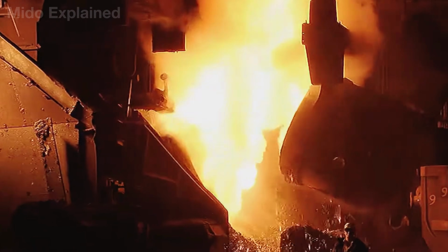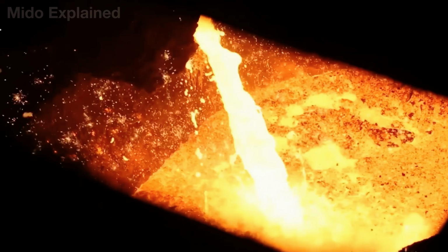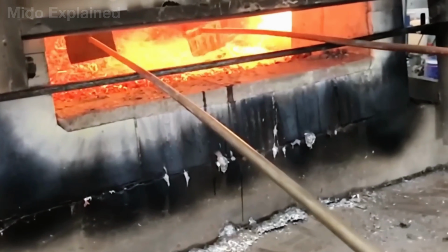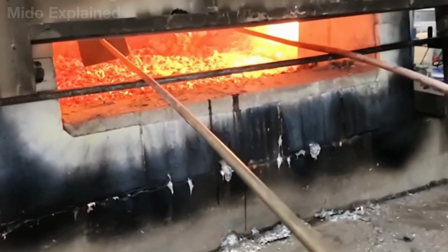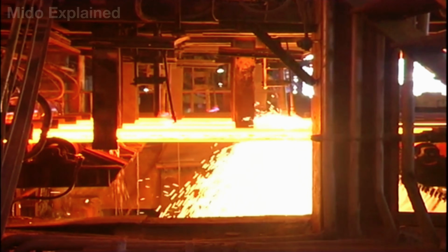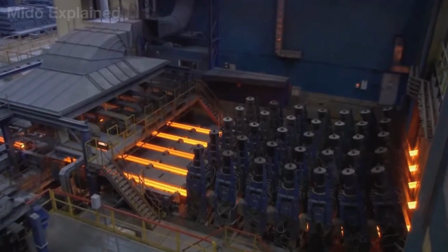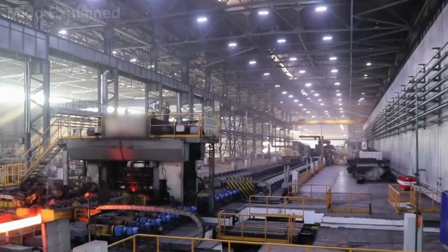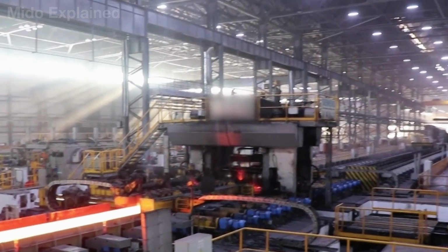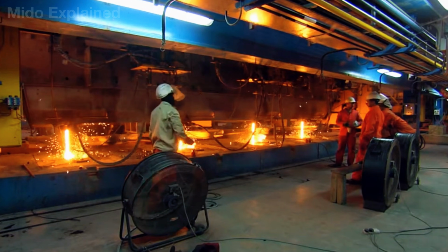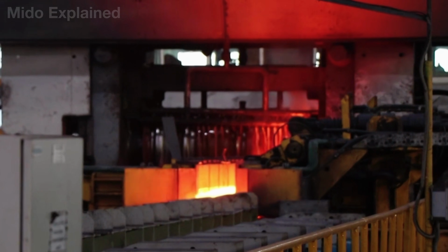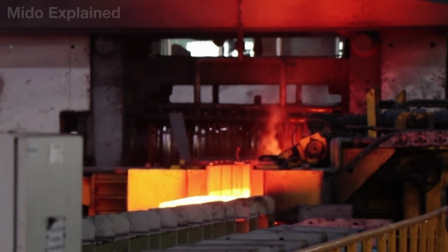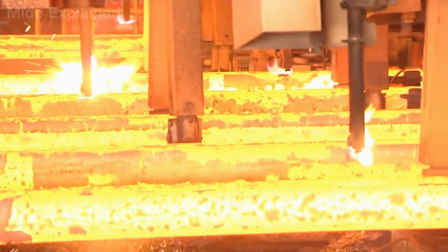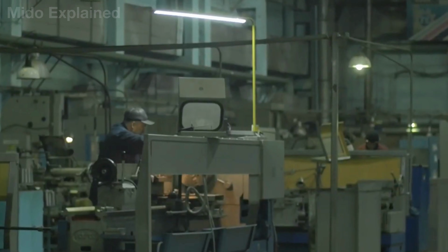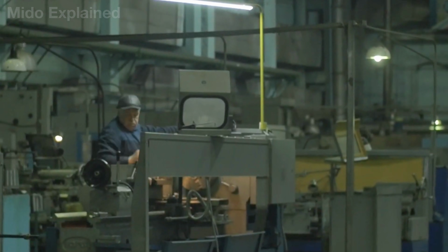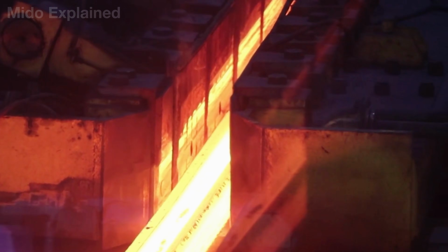After leaving the furnace, the molten steel is cast into ingots and transferred directly to the holding area. The steel billets are not immediately rolled but must undergo a heat treatment and preparation phase. They are transferred to giant reheat furnaces, where the temperature is maintained between 2,200 and 2,400 degrees Fahrenheit. Depending on the size of the billet, this process can last from 1 to 3 hours to ensure even heat distribution from the outer shell to the core of the steel.